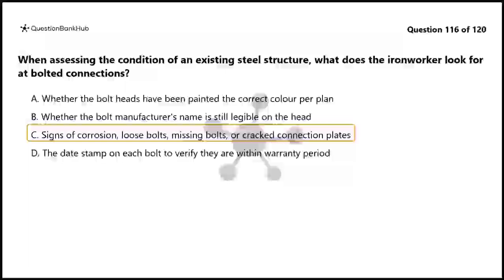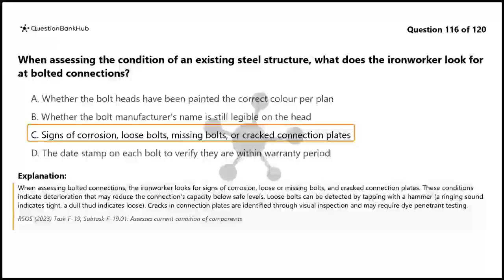The correct answer is C. Signs of corrosion, loose bolts, missing bolts, or cracked connection plates. When assessing bolted connections, the ironworker looks for signs of corrosion, loose or missing bolts, and cracked connection plates. These conditions indicate deterioration that may reduce the connection's capacity below safe levels. Loose bolts can be detected by tapping with a hammer: a ringing sound indicates tight, a dull thud indicates loose. Cracks in connection plates are identified through visual inspection and may require dye-penetrant testing.